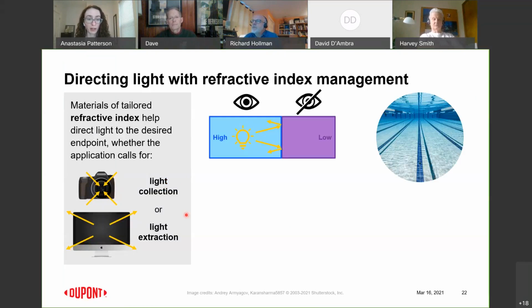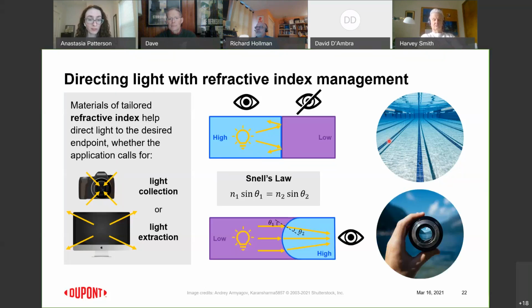So just as a reminder of how refractive index at interfaces work, if you go from a high refractive index medium and try to get light into a low refractive index medium, there's often reflection at this interface, and it depends on that difference in refractive index across the interface. So for example, if you've ever been swimming and you've gone underwater and looked up at the surface of the water, you see a lot of reflection, and that's because of that refractive index difference. If you have the opposite situation, then you don't get reflection, but you do get refraction.